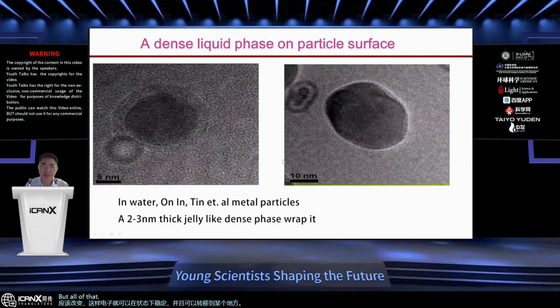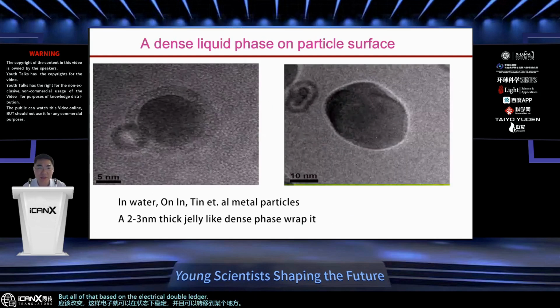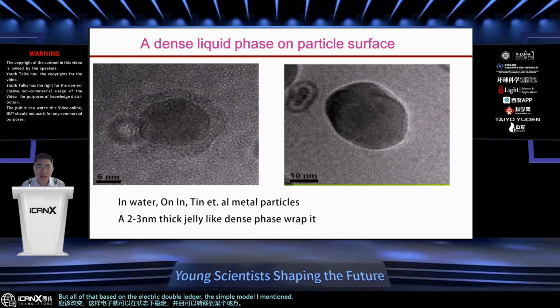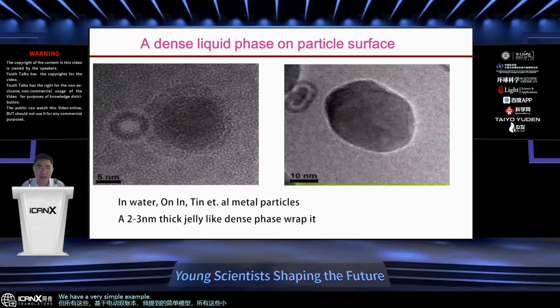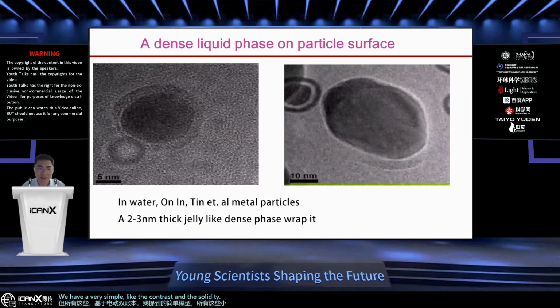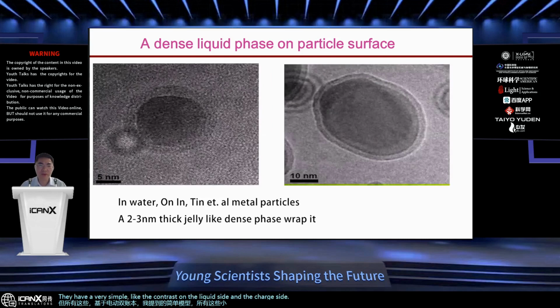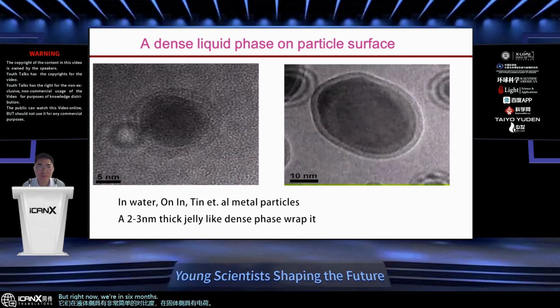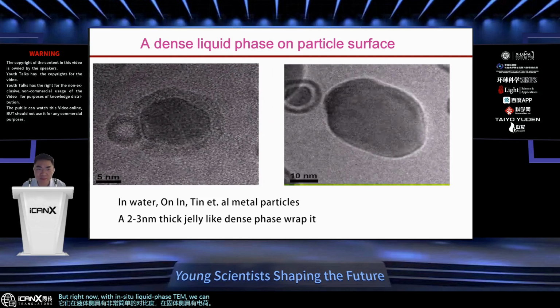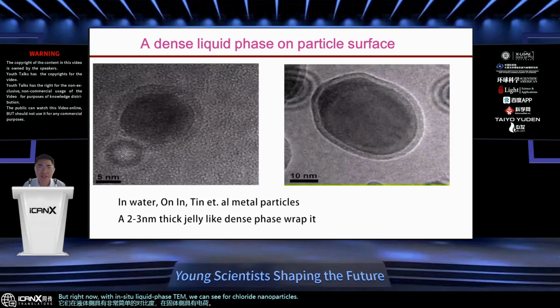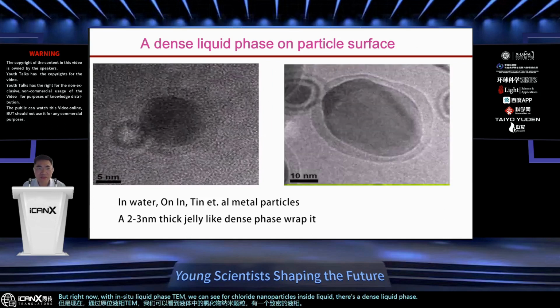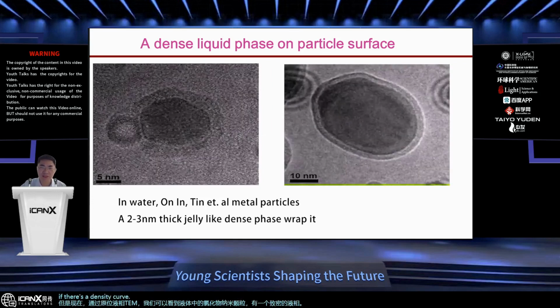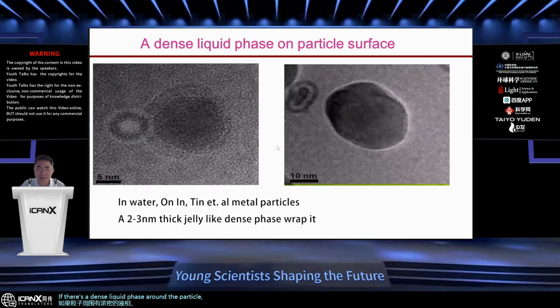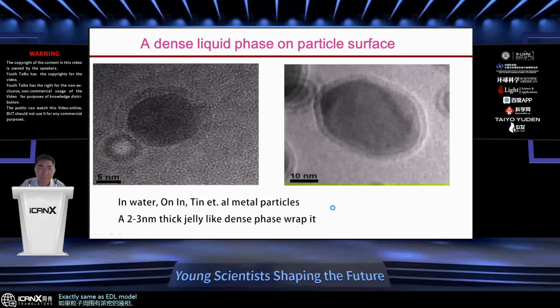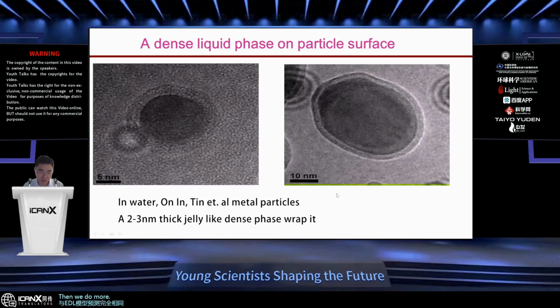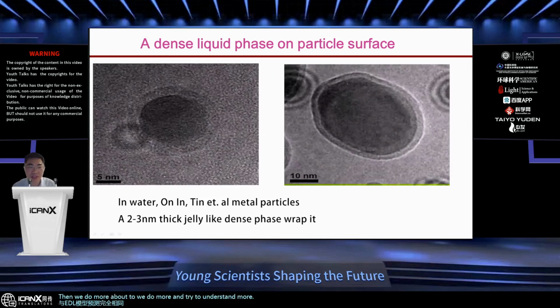But all of that is based on the electrical double layer, the simple model I previously mentioned, with the counter ions on the liquid side and the charges on the solid side. But right now, with in situ liquid phase TEM, we can see that for colloidal nanoparticles inside liquid, there's a dense liquid phase around the particle. If there's a dense liquid phase around the particle, that couldn't be exactly the same as the EDL model predicts. Then we do more and try to understand more about the electrical double layer.